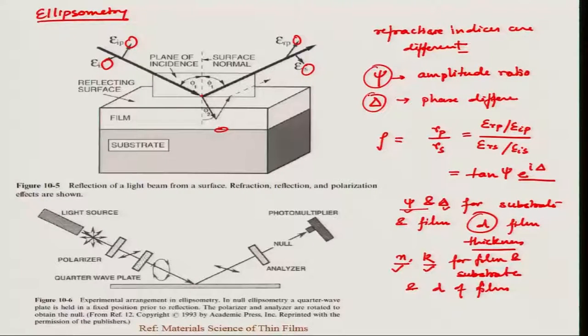Again, you can use 2 different approaches in this. One is multiple angle of incidence, or MAI, in which lambda remains fixed, and you change the angle of incidence, and you observe psi and delta at those angles. You measure psi and delta, and then you correlate by a computer model to n, k and film thickness. Or you can use what is called spectroscopic ellipsometry,